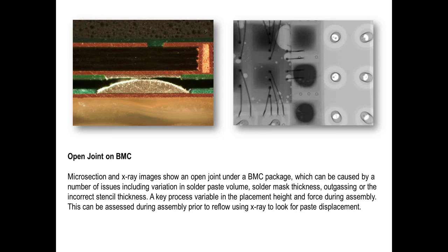And we can actually get the same sort of phenomena of gassing, but not gassing physically from the surface, but gassing because of trapped volatiles. And on this type of component, it's quite common to have solder resist define the pads on the package itself. So you've basically got a resist window and a termination you're soldering to.